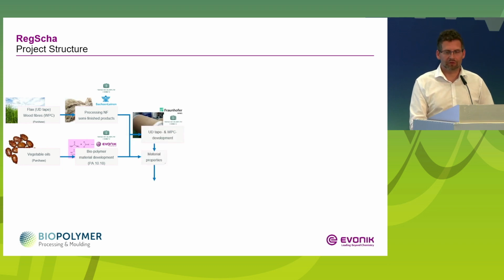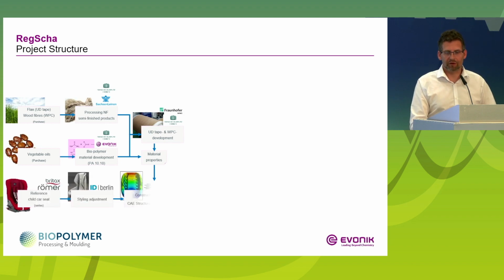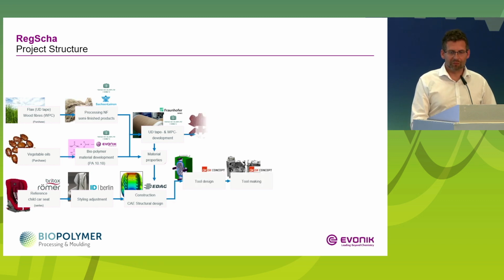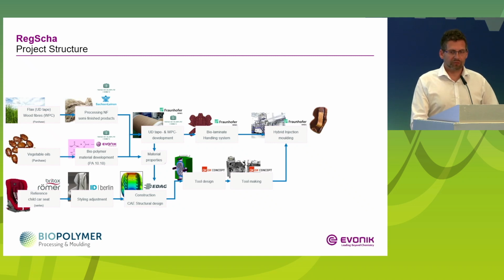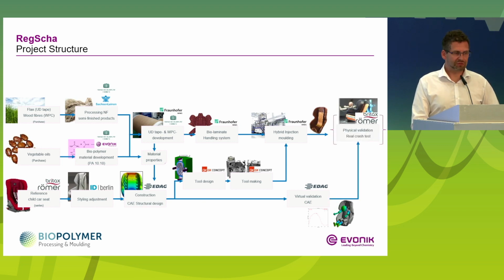On the one hand, we developed a WPC recipe and UD tape, and determined the material properties. And in parallel, we came from this state-of-the-art geometry from Britax Römer, from the child safety seat, and adjusted the styling and had a construction which was composite conform, and could then go into the tool design and tool making. And out of these UD tapes, we produced a laminate, and this was taken by a handling system into a hybrid injection molding to produce this bio-based and natural fiber reinforced child safety seat. And at the end, we had a validation, first virtual, and then, what is not done yet, we want to do a physical validation with a real crash test.